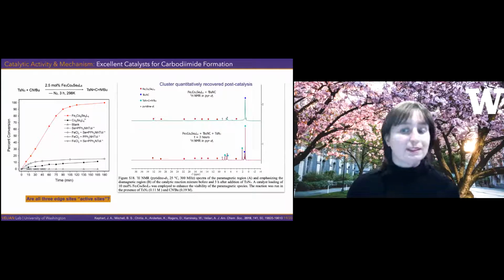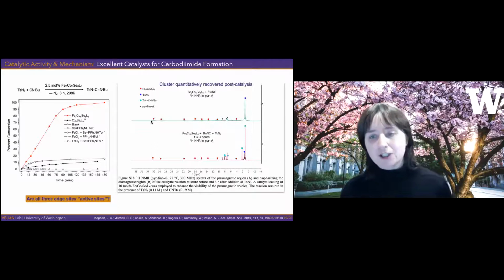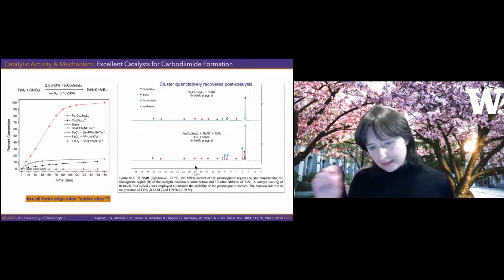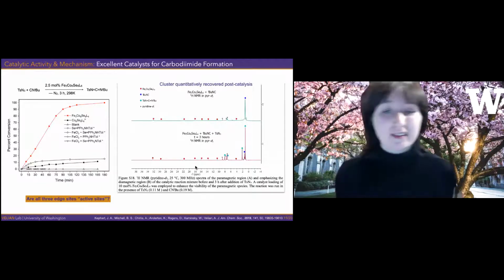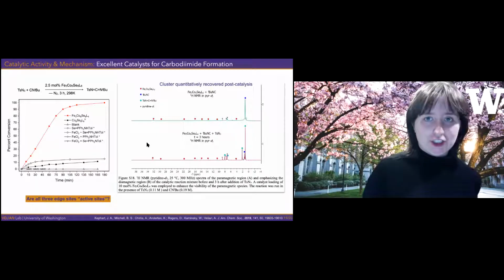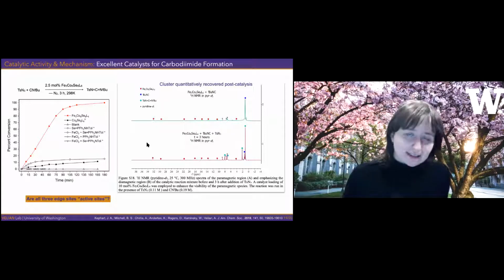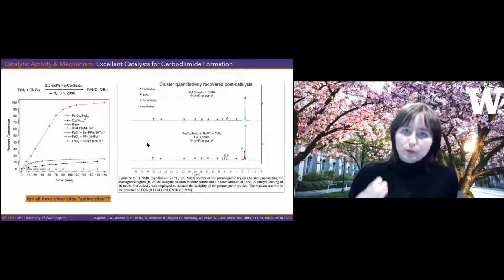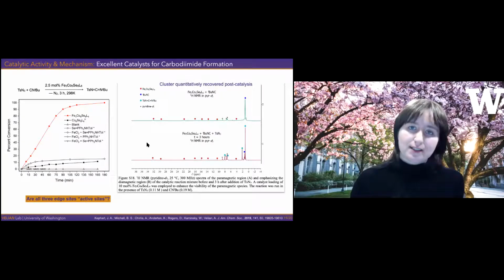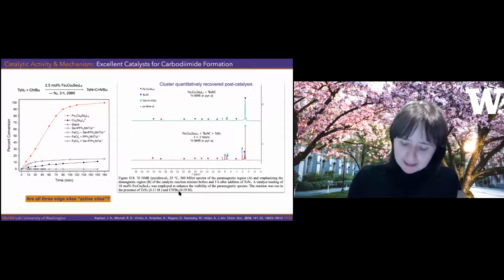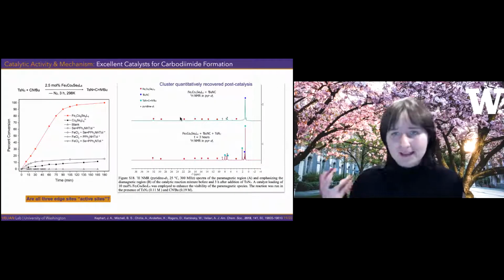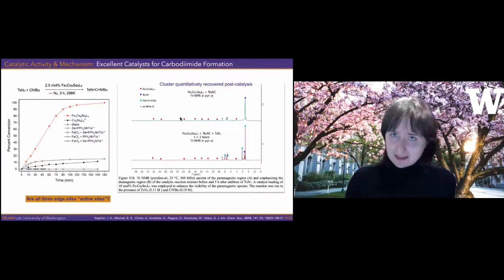And then what was especially interesting is that at the end of the reaction, our catalyst, I'm showing here the NMR before and after, and labeled in red is our catalyst. The paramagnetic features associated with it, and we actually see no decomposition of the catalyst, and that's kind of cool because it's a little bit unexpected, and it just gives us hope that we do in fact have these edges as catalytically active sites. And it's not trivial to probe whether that's the case, because the transformation is so fast that we're just unable to see intermediates and isolate them.